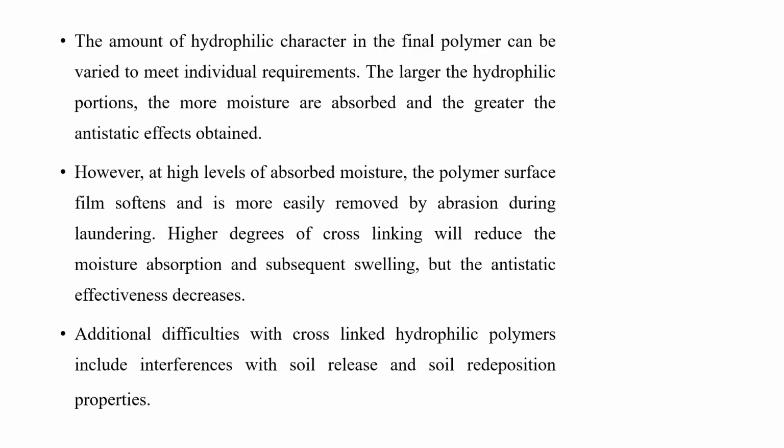The amount of hydrophilic character in the final polymer can be varied to meet individual requirements. The larger the hydrophilic portions, the more moisture is absorbed and the greater the antistatic effect obtained. A higher degree of cross-linking will reduce the moisture absorption and subsequent swelling, but antistatic effectiveness decreases. Additional difficulties with cross-linked hydrophilic polymers include interference with soil release and soil redeposition properties.